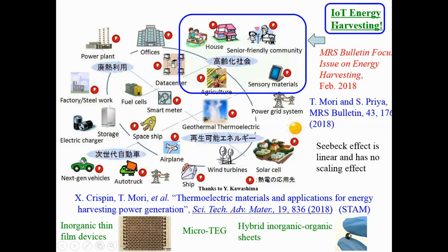So the idea, of course, is energy harvesting to dynamically create electricity, so you don't need to change the battery. So maybe it will be a charged battery, but in any case, you have some dynamic system to gather the energy. And for us, this is thermal energy, thermoelectric. So it's particularly good for us because the Seebeck effect is linear, as we have seen, and there's no scaling effect. So for small heat, like body heat, you can get a small electricity, which could be enough to power a sensor. So this is sort of the idea.